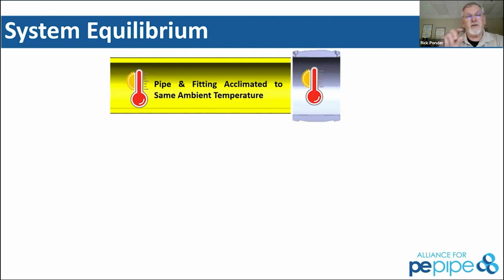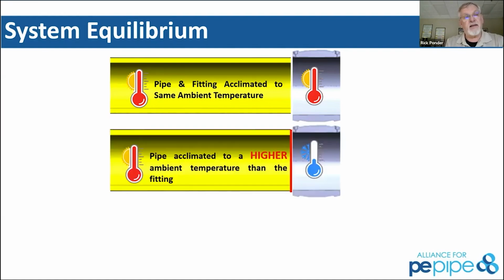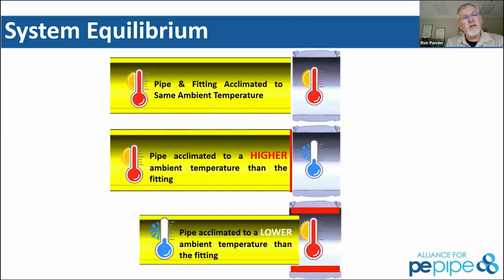In other words, if both the pipe and the fitting are the same temperature, everything's going to go together fine. The interfacial gap is not going to be too large that it can't be filled as the plastic melts and expands. When you have a pipe that's at a higher temperature and a fitting at a lower temperature, the pipe could be larger than the fitting and it may not go into the fitting easily or at all. If the pipe is colder than the actual fitting, then it's going to be smaller, then it will slip in easily, but the gap may be too large for the fitting to actually heat up and expand and close the interfacial gap like you need to do to get a good fusion.